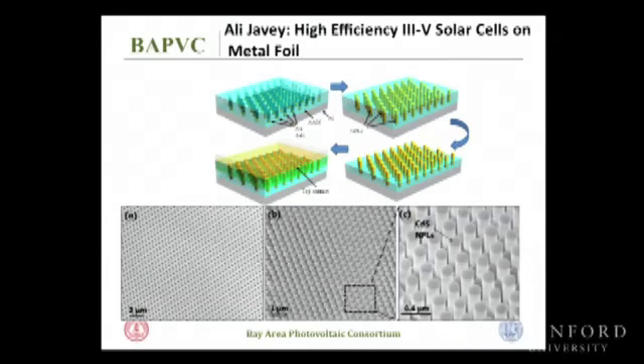He's trying to make III-V solar cells on metallic foil. We know it's very hard to grow single crystal on metallic foil. For making a III-V solar cell, you need a substrate. You need to do MBE, MOCVD growth of epitaxy. What Ali is trying to do is take advantage of what's developed in nanotechnology, using tiny nanoparticles as catalysts to grow nanowire nanopillar arrays, and then he can peel off. This is now possible on stainless steel substrate.